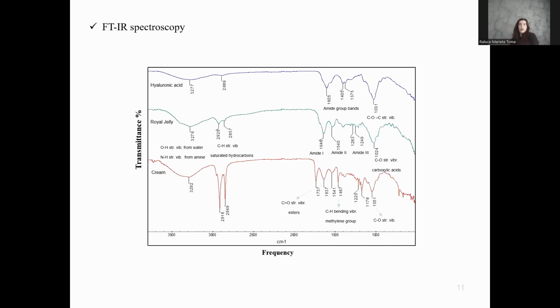We have also FTIR measurements for the pure compounds, for the hyaluronic acid and royal jelly, and for our dried cream sample. We observed many shifts in the spectrum of our cream because there are many interactions between active groups from polyphenols and fatty acids with hydroxyl groups from our biopolymer. So we have to do a mass spectrometry analysis further.